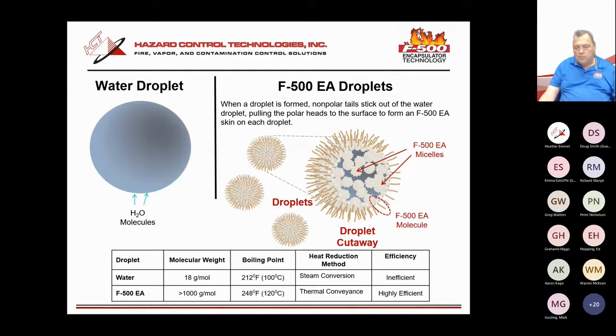This is just showing, again, a spherical micelle with the molecules encapsulated inside, separating the fuel from the oxygen on a chemical molecular level. The second thing that I think is very important to understand is here you have plain water, and it has a molecular weight, it has a boiling point, and we know very clearly the heat reduction mechanism of plain water is steam conversion. So the outer molecules of this water droplet heat up from room temperature where they come out of the sprinkler head up to 212 and convert to steam, and that's what slowly reduces the heat.